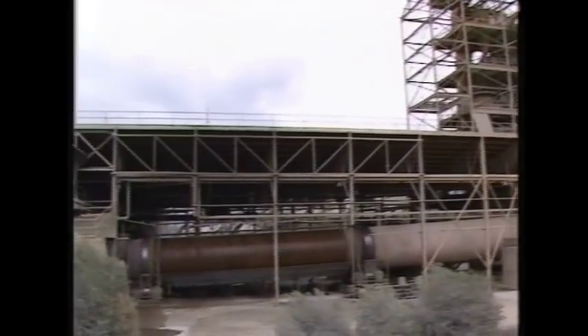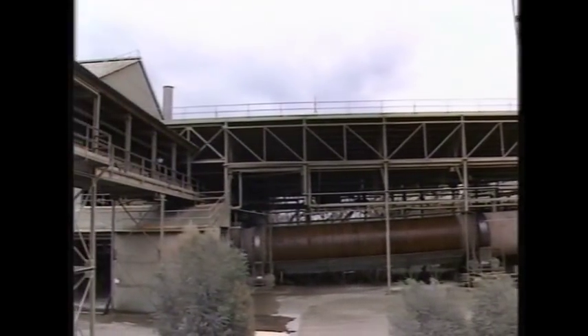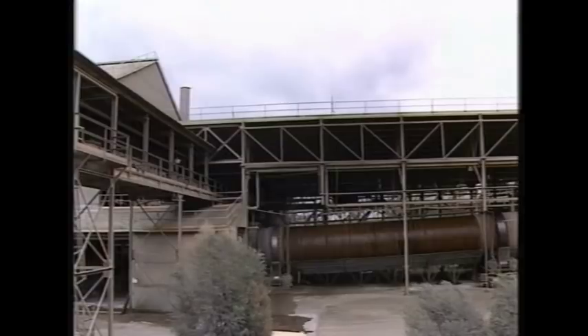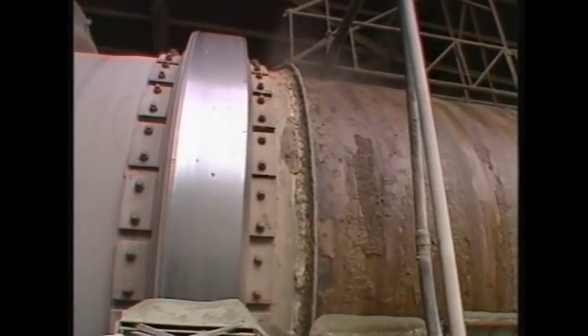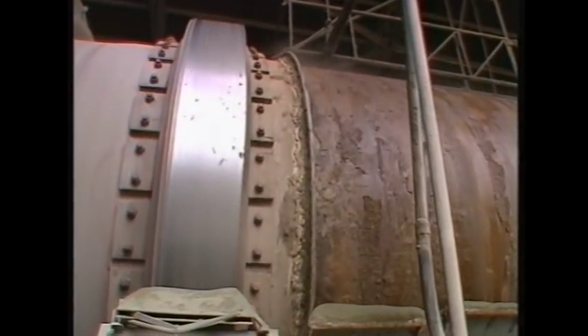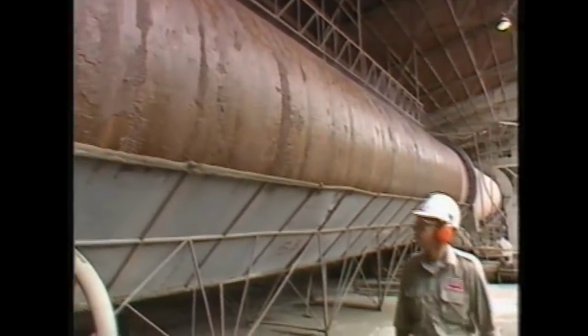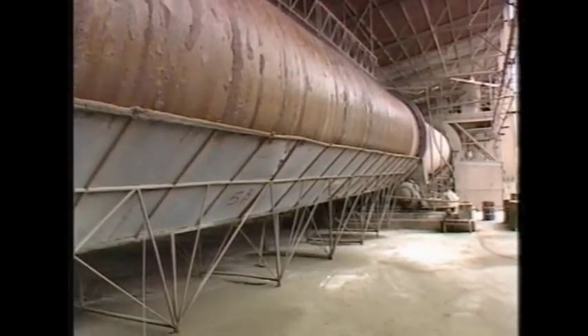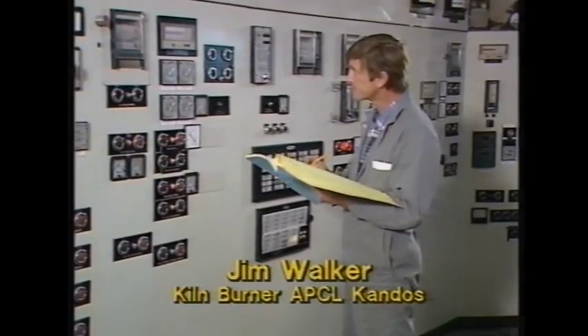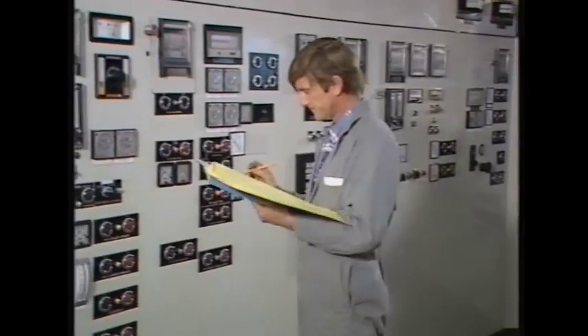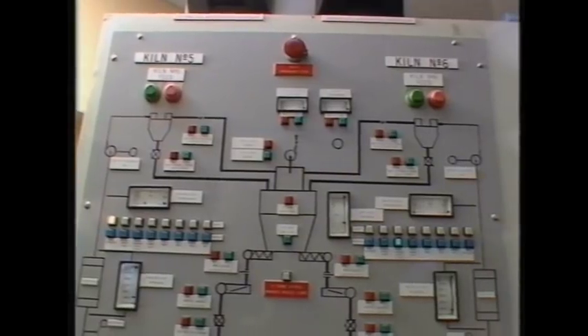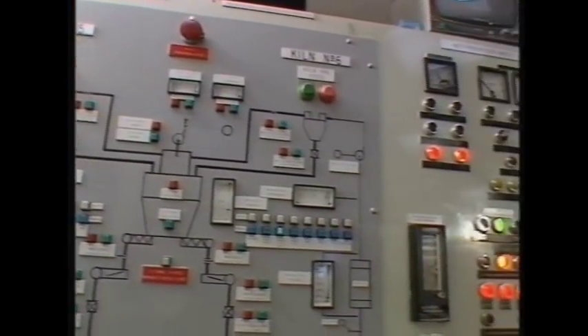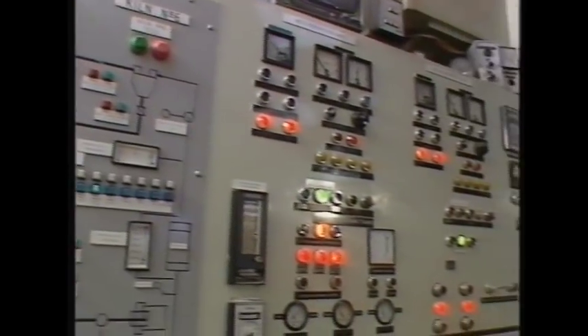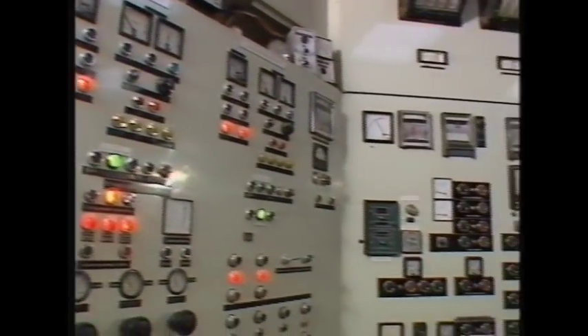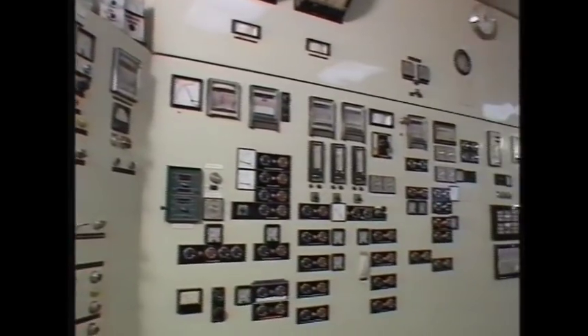This rotating kiln is lined with refractory brick. The material enters the kiln at approximately 700 to 800 degrees centigrade via a heat exchanger, and the discharge temperature is approximately 1500 degrees C. In the kiln control room, the burning process is precisely monitored with complex instrumentation. A 24-hour watch is maintained to assure constant quality control.